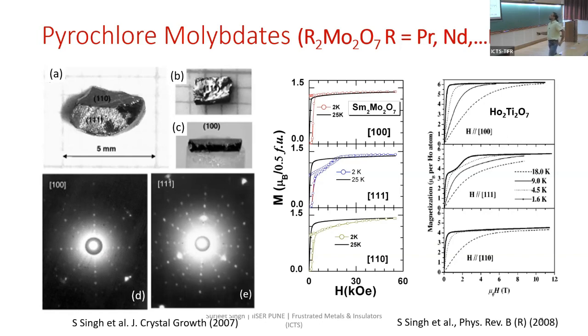So in molybdates, in fact, the field of stability, structural stability is pretty large. But the problem here is that the moly sublattice orders ferromagnetically. And once the moly sublattice is ordered ferromagnetically, then it's very difficult to see what the rare earths are doing. And the problem with the crystal growth is that molybdenum, first of all, keeping its oxidation state to 4+ is rather non-trivial, because it tends to go to 5+ or 3+ rather easily, depending on what the growth conditions are.